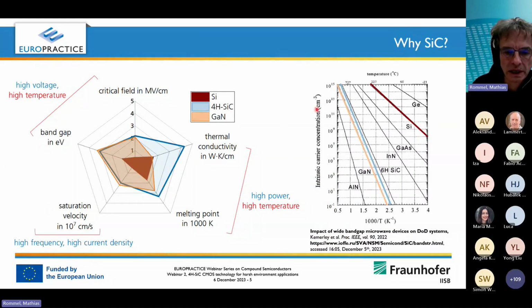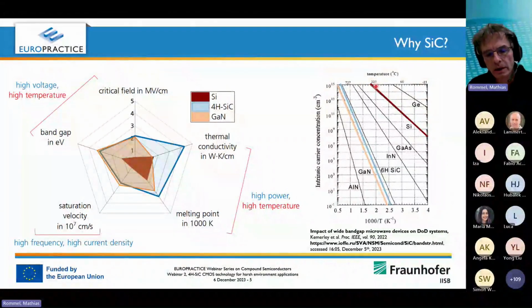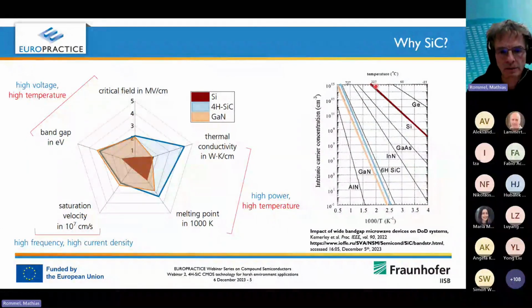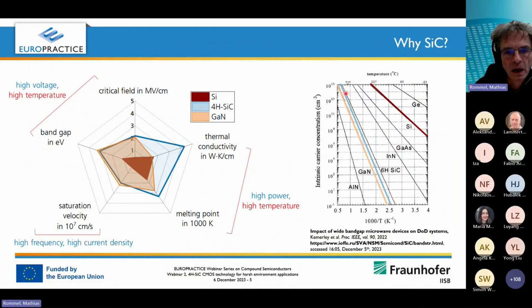What can you see here? It's the intrinsic carrier concentration, which just depends on the band gap and the temperature. There you can see that, for example, for silicon, you achieve an intrinsic carrier concentration of 10 to the power of 15 already at around 200, 250 degrees C. That's why you cannot get any efficient doping anymore at these temperatures. And that's why the very high temperature applications for silicon just rely on fully depleted SOI and not standard silicon technology anymore.